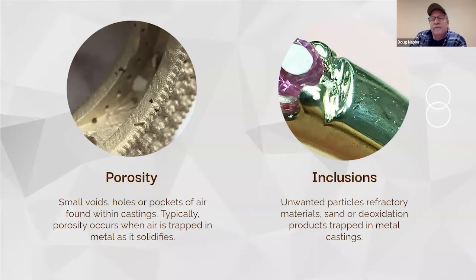If it's porosity, usually it's really small, like almost sponge type surface. And it will usually happen in the thickest area, just because of the way when metal goes from a liquid state to a solid state, when it's making that transition, it's actually shrinking just a little bit. And what it wants to do is it wants to pull molten metal into that area that it's shrinking. So if you have a piece that, say, you got a thick area that's cut off from the rest of the piece that's not sprued there, then when that metal goes from a liquid state to a solid state and there's nothing for it to draw into itself, then it has a breakdown, and that's where you see the casting porosity.